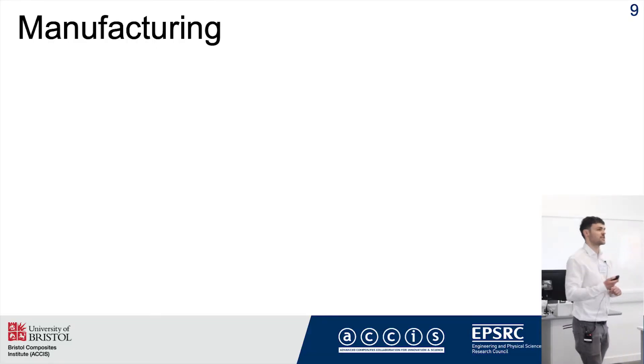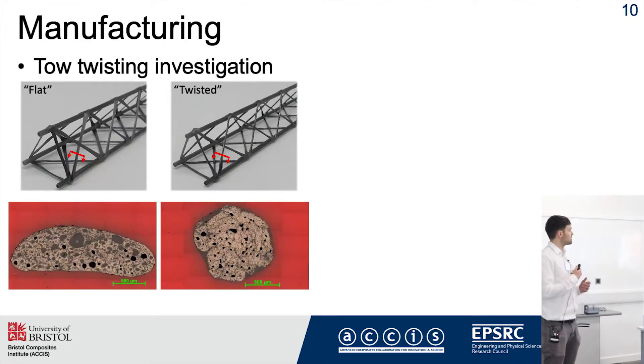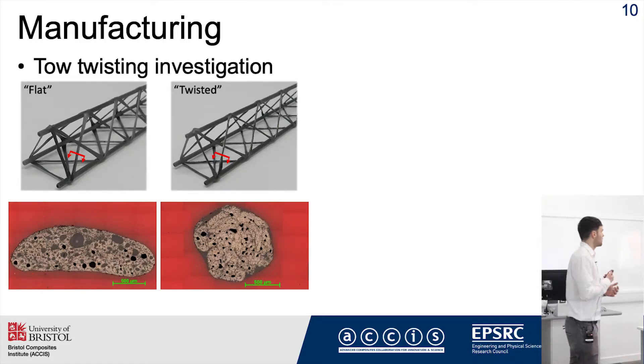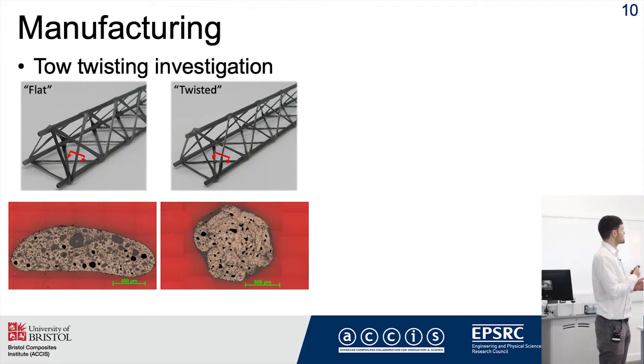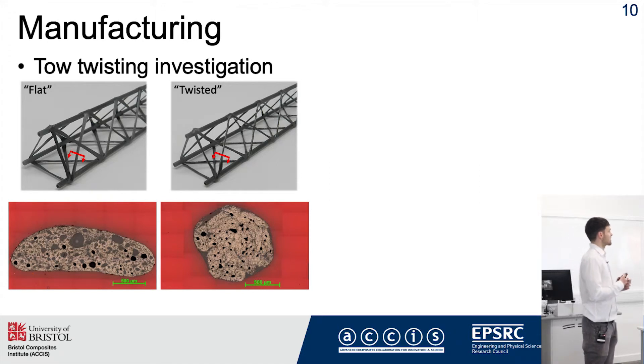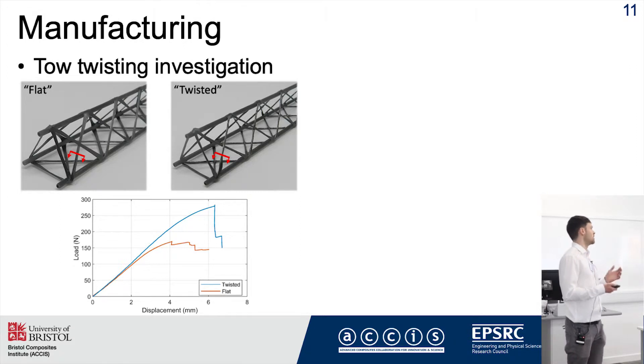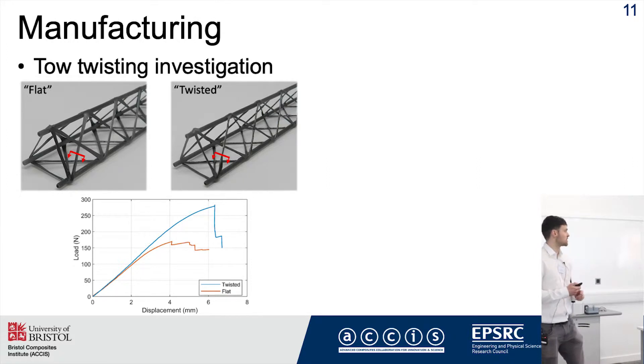We've been doing a lot of manufacturing work. One of the studies we did was looking at the effect of twisting the carbon fibre tow. What we found was if you twisted the carbon fibre tow, you get shear members with a circular section — that's the image on the right. What we found is that really improves the buckling resistance of the shear members and creates a better structural efficiency.